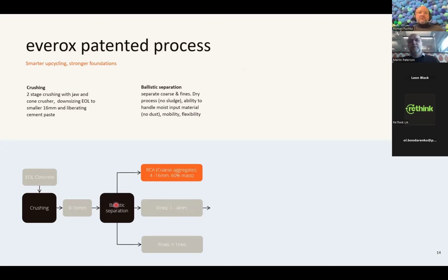In the ballistic separator, we get 3 fractions out of that machine. Basically, it's a fast-turning rotor which hits the material, and then depending on the particle size and on the weight of the material, we go to different areas of the machine. So we get 3 fractions out of that.